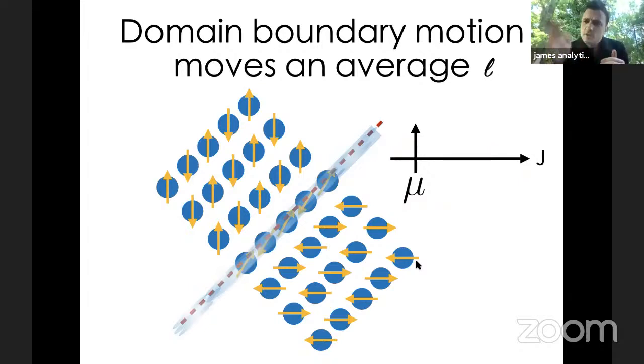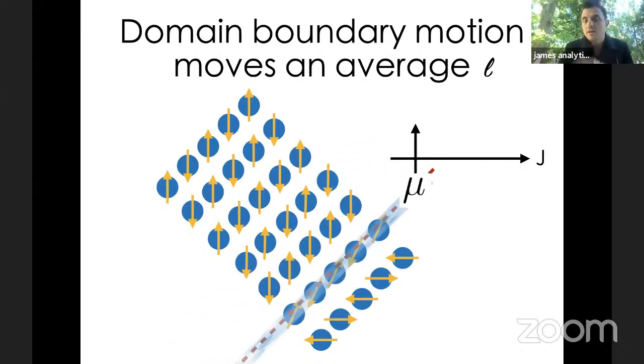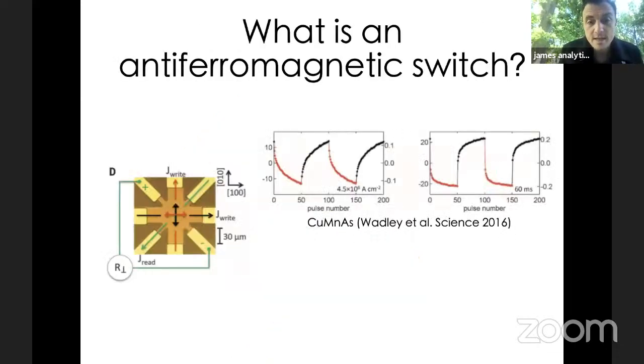Now, why do you get the sawtooth-like structure? Again, there's probably people here that can explain this better, but my understanding is that we basically think that most of the effects happen at the domain boundaries. And so by applying multiple pulses, you can shift that domain boundary further and further along. And so you can change the resistance state from the Néel vector in one direction to the Néel vector in the other direction. So that's the basic understanding.